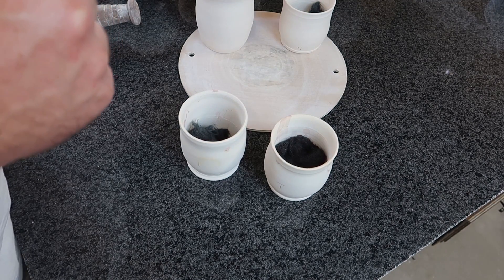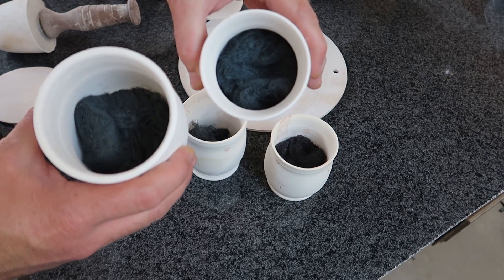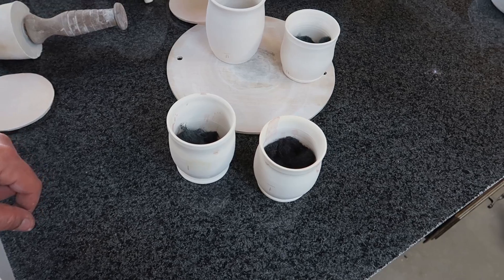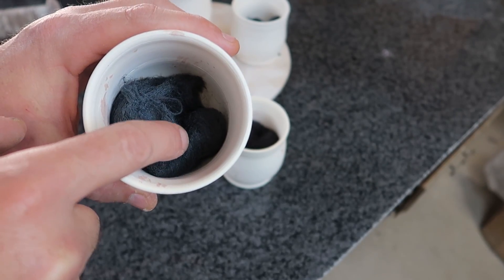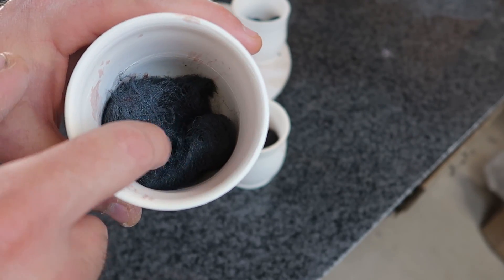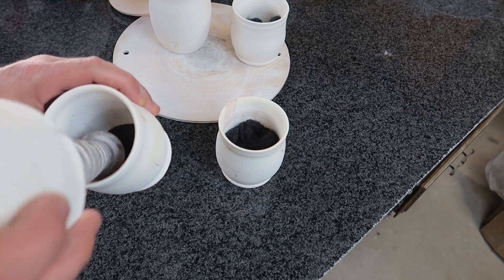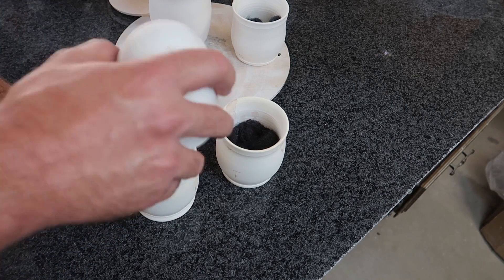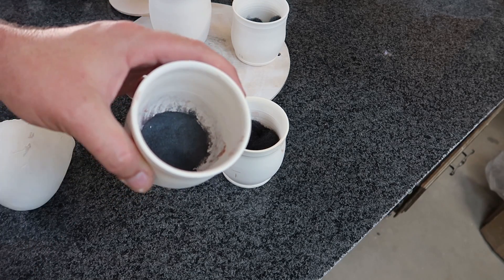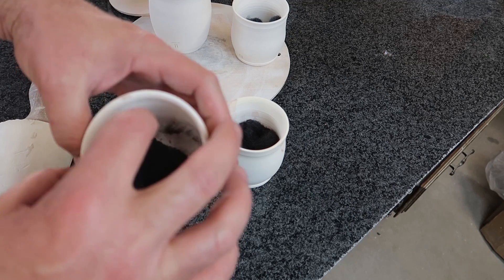I'll show you the covered and uncovered no-treatment pieces — they look identical. So I'm already thinking that any sort of pre-treatment is not necessary. When I touch it, it feels super soft or crunchy, like sugar crystals. I have a handle on this plaster-forming tool and it's almost completely powdered already. If you know why this didn't turn red, let me know — I don't know why I expected iron oxide to be red like rust, but in an oxidizing environment apparently it's not.